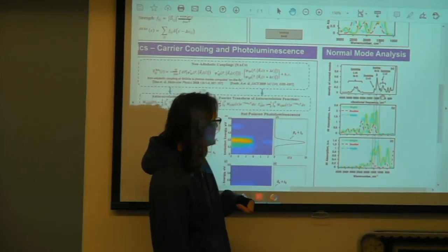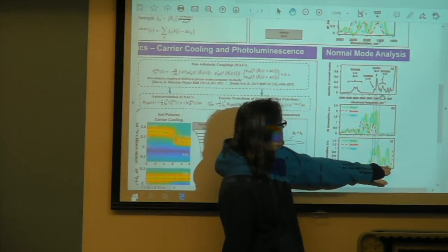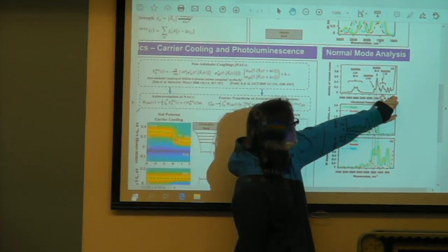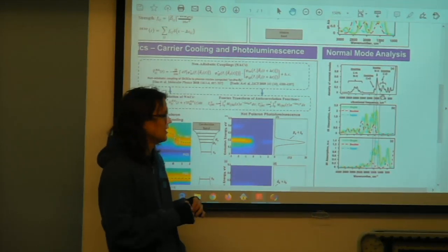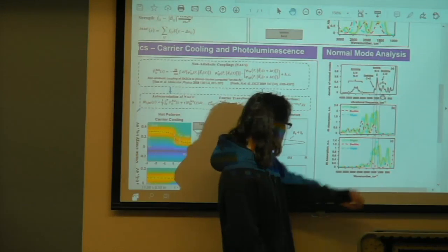One thing that stood out was for the positive polaron, the lower energy transitions are in resonance with, I didn't label them here, these lower mode frequency vibrations, and these specifically come from the perovskite inorganic core itself. Those typically range between 100 and 400, 500 wave numbers. So the positive polaron is in resonance with the perovskite lattice.